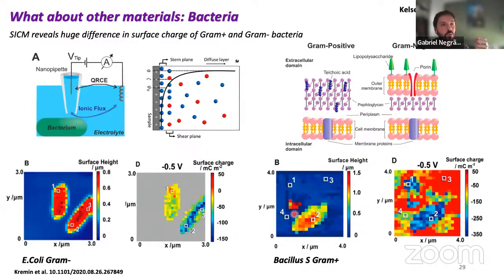And we can see here those are the graphs of surface charge and surface distribution. They do have a difference between them. The surface charge is quite heterogeneous over a single bacterium. Each one of those individuals here is one bacterium, and this is just a topographic map, and this is the surface charge map we can get from this technique. And more than that, not only is the surface charge different, we can now probe the transport properties at this interface, on this polyelectrolyte. We did that. We have a COMSOL model that accommodated for that, and we can actually see that part of what we're doing is probing this polyelectrolyte.